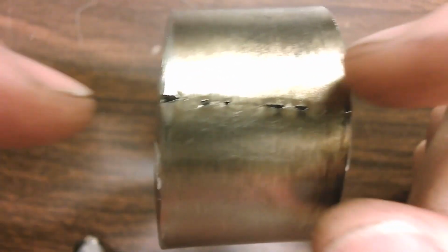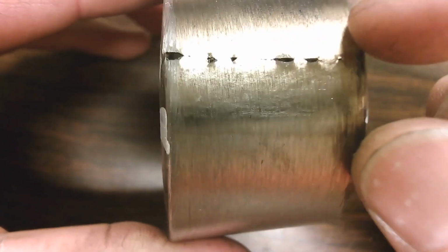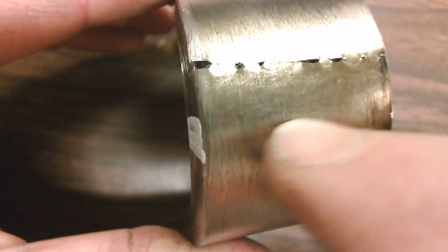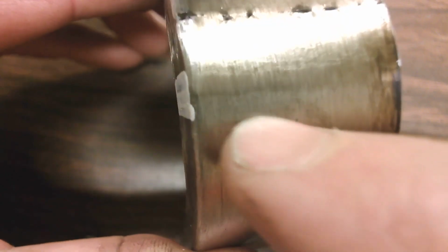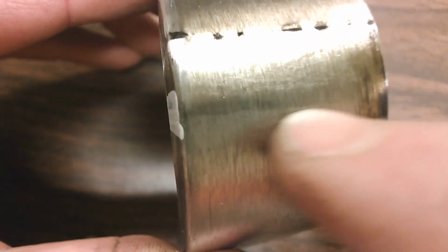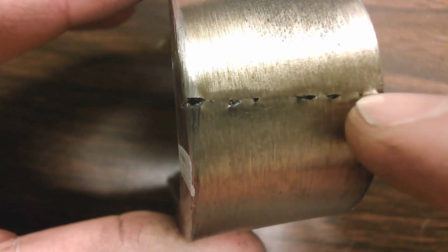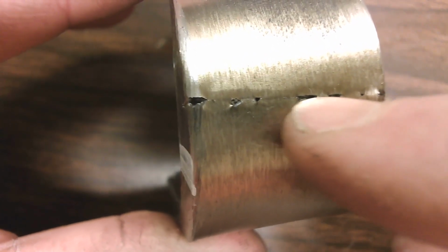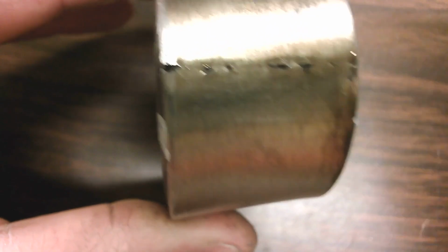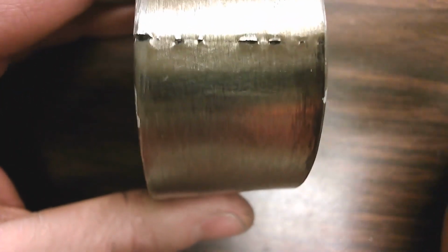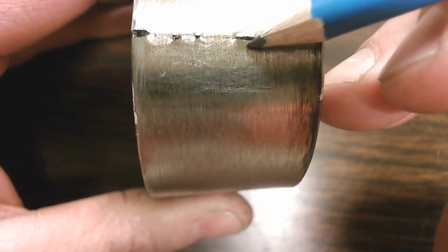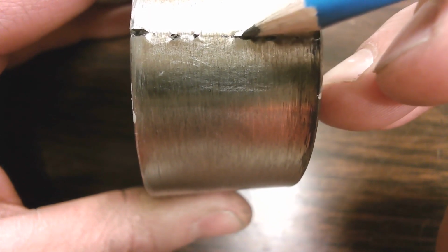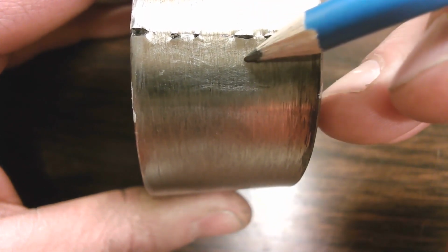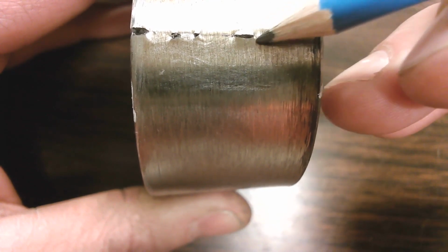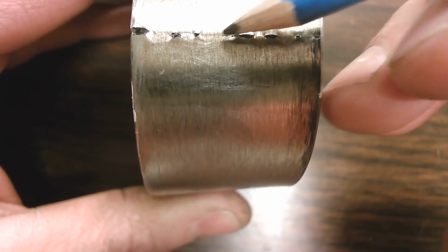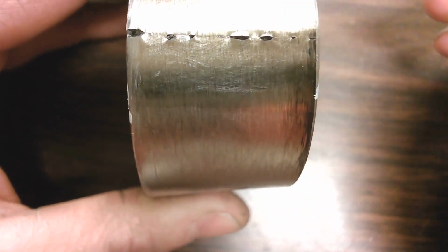So again, we can see this is clearly the root for a couple reasons. We can see the heat signature here kind of ends. Might be a little hard to see on the camera, but right there, there's kind of a shadow line. And then clearly we've got lack of fusion going on right here. You can see the original base metal, and so there's a nice straight line. You can see the weld bead didn't actually fuse onto the base. So here's the base metal, here's the weld bead on the root opening there, and it just didn't quite get it in a few spots there.